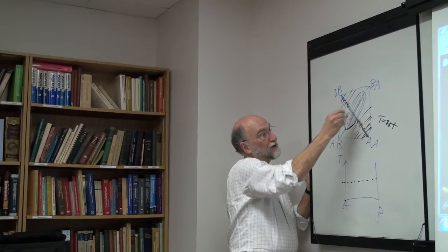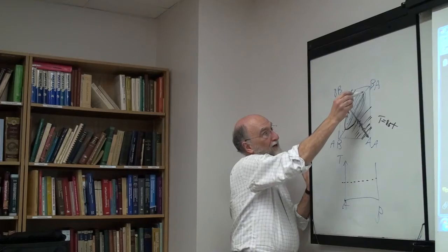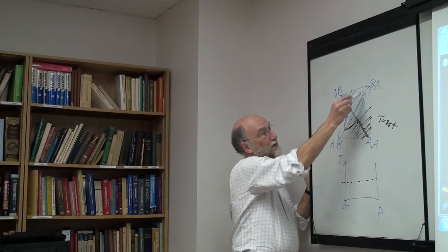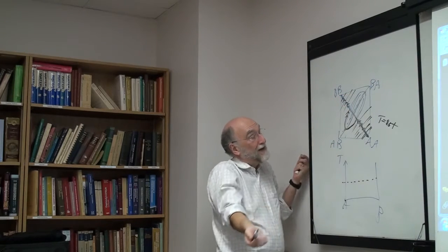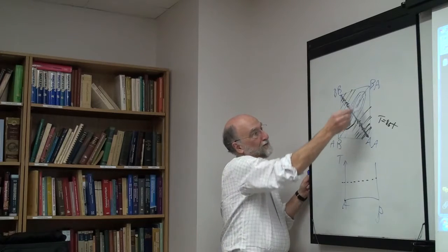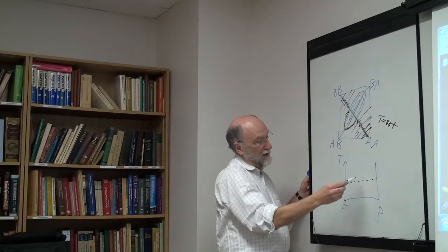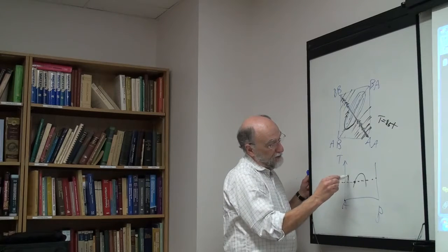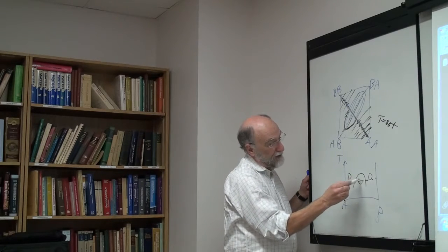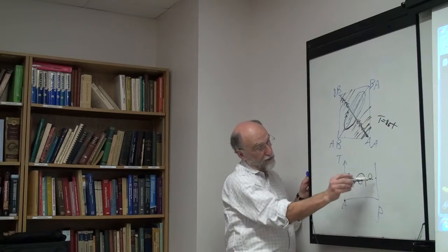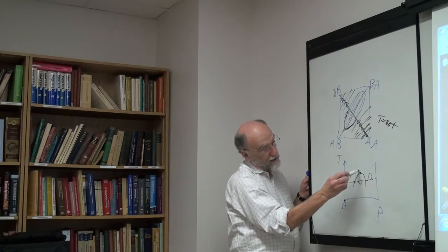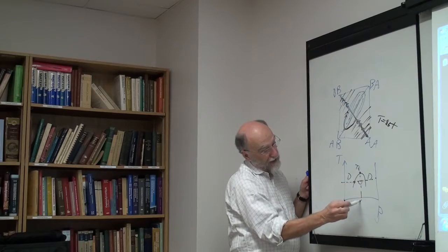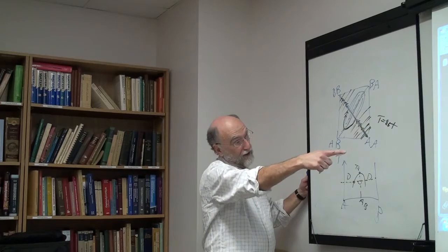Or you could consider that you're just going straight across here, you're going through a disordered region, then you're crossing the ordered region where you have the ordered phases. You could consider you have two ordered phases, AB and BA, in equilibrium if you like, but they're identical. So it's the same thing, and then you come out this end. As you move across here, you're going to get a disordered region, and then in the center you'll cross an ordered region. So this would be your critical temperature at exactly 50%. That's what you've calculated here.